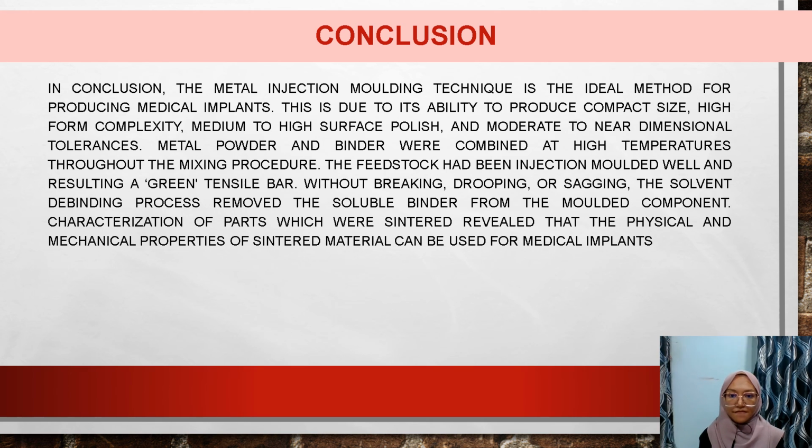procedure. The feedstock had been injection molded well, resulting in a green tensile bar. Without breaking, drooping, and sagging, the solvent debinding process removed the soluble binder from the molded component. Characterization of the sintered parts revealed that the physical and mechanical properties of sintered materials can be used for medical implants.